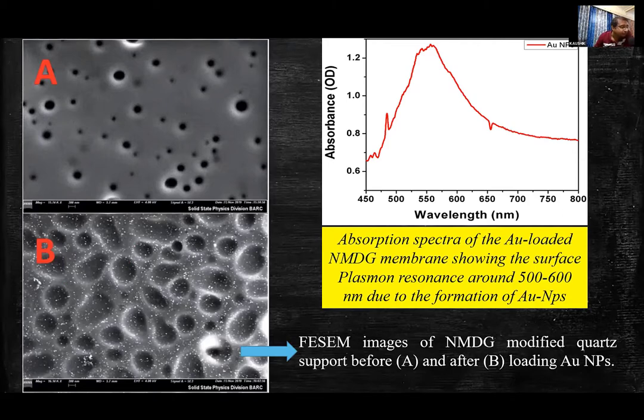And I have also determined the particle size distribution of that gold nanoparticle. It was seen that the size distribution is around 10 to 25 nanometer. So both this FESEM image as well as absorption spectra clearly suggest that whatever gold is trapped inside that NMDG membrane is in the form of nanoparticle, which we are going to use as an internal standard.